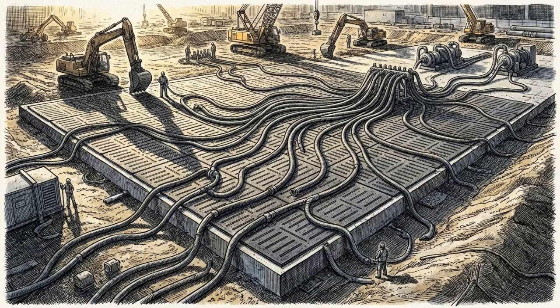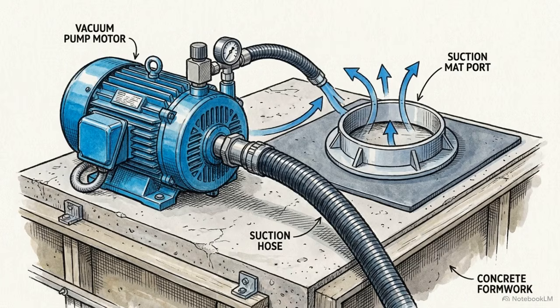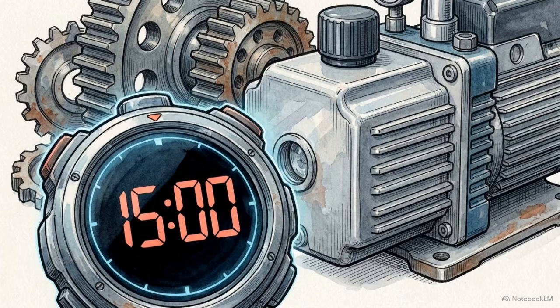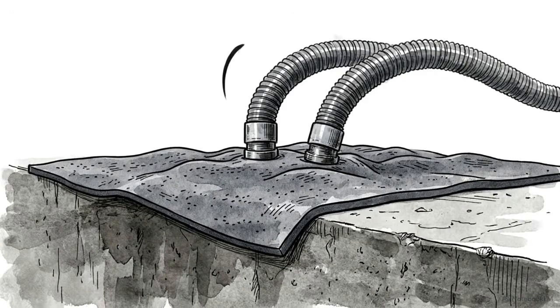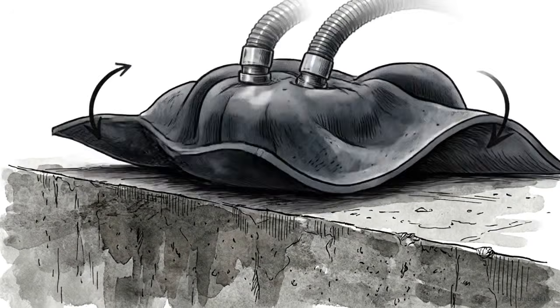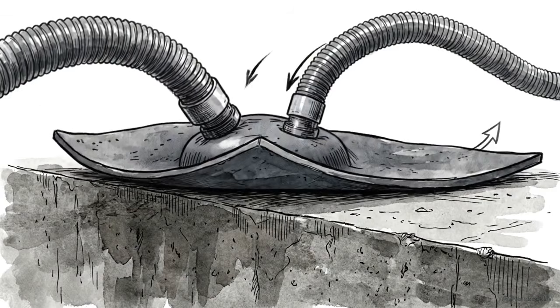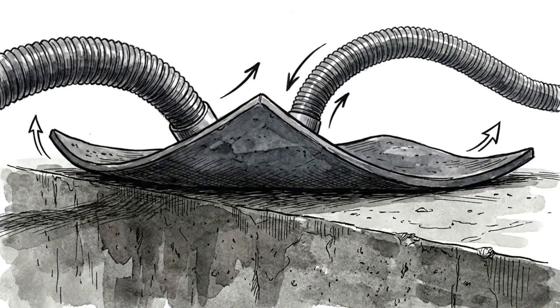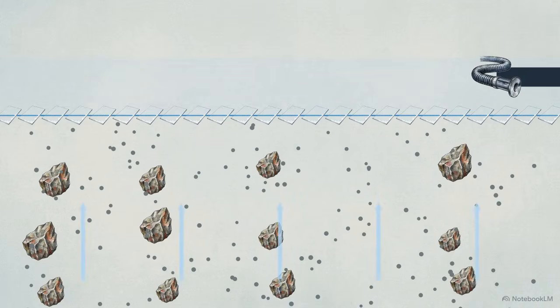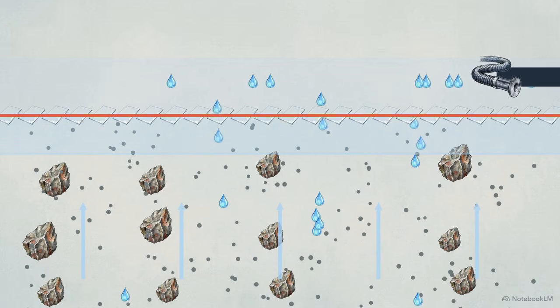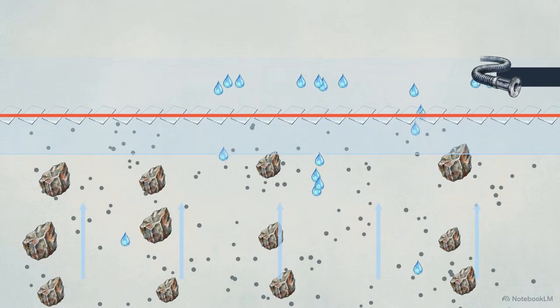A high-capacity 3 to 5 horsepower vacuum pump is then connected directly to the sealed suction mat assembly and activated. Operational timing here is strictly enforced. The system must sustain negative pressure across the slab for exactly 15 to 20 minutes. The moment the pump turns on, it evacuates the trapped air from between the mat and the slab, creating a powerful pressure differential. Looking at an extreme microscopic cross-section, negative pressure pulls water droplets up through vertical capillary channels, while